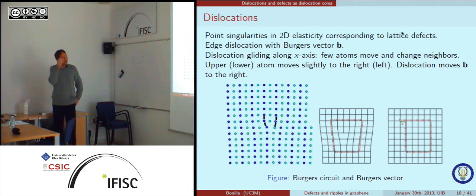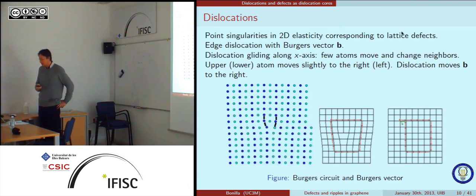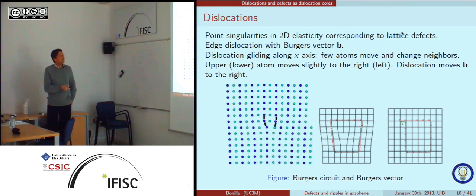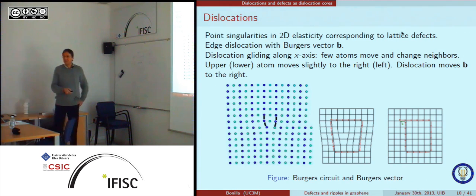Here I'm just reminding you what a dislocation in two-dimensional elasticity is. This is an edge dislocation, which means that you have an extra half row of atoms here with respect to the rest. And this is the core of the dislocation, about this point. If you start here, move around on a closed polygon and go back there, and you try to do the same in the pristine lattice, you discover that there is one missing vector. So you don't close the circle, counting exactly the same number of lattice vectors from here to there. The vector that joins these two ends is the Burgers vector, and that marks the direction in which it is easy to move the dislocation.